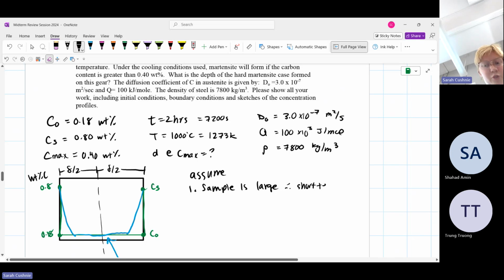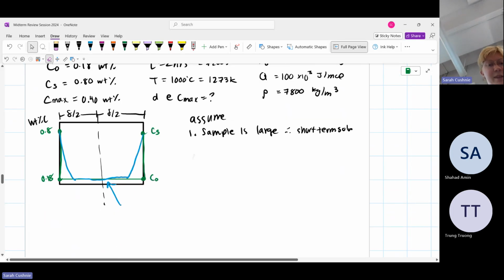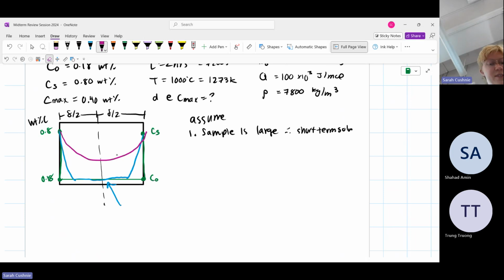Therefore, short-term solution. If you had a really, really thin wafer of steel and you put it in these conditions for 2 hours, it's likely that you would diffuse so much, you would get something like that. That's a long-term solution. But we can assume that our sample is large enough, we're not going to reach that state.